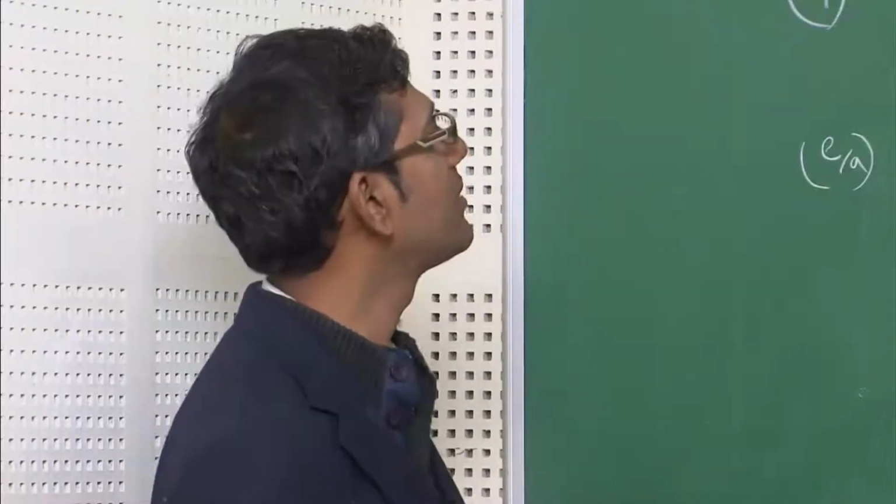But the second one, which is stabilized by size factor, for which I will show you some structure details in the slides, are called Laves phases, and there are 3 types of Laves phases. One is called MgCu2, which is cubic structure, MgZn2, which is hexagonal structure, and MgNi2, which is again hexagonal structure, but with a double unit cell of hexagon. It will be very clear to you when I show you the slides, and I gave you examples of those compounds.